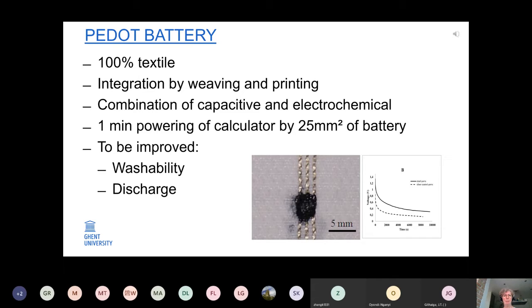At the end of the research, we managed to power a small calculator, a simple traditional calculator, for approximately 1 minute, and this with a battery of 5 by 5 millimeters, so 25 square millimeters. And this shows that you can provide quite a large power capacity when you exploit the full surface of the textile.